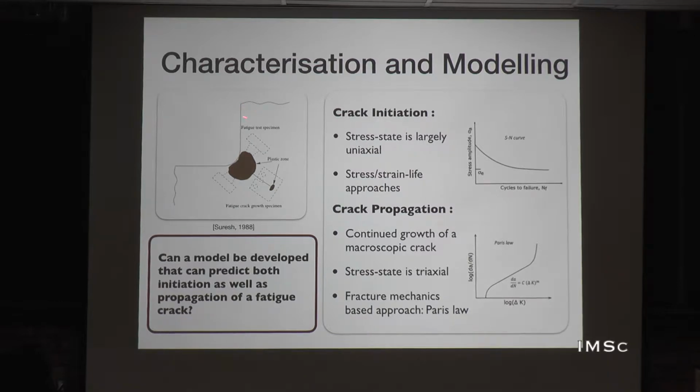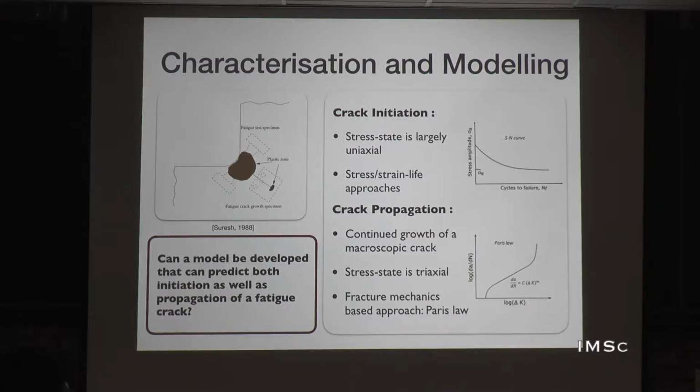So what you have here is material. It has a free surface, like this. For instance, in the windows of aircraft, there is a corner there. There used to be a corner there, which had its fillet, but probably not enough. But these kinds of stress raising elements are always going to be there. Whatever you design, there are going to be locations which are more critical than others, and typically that's where the fatigue crack initiates.